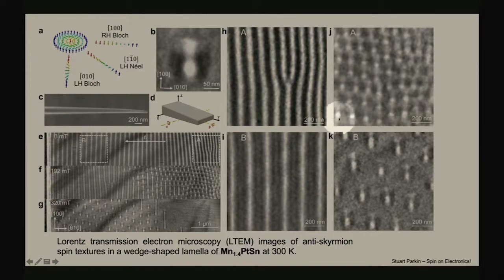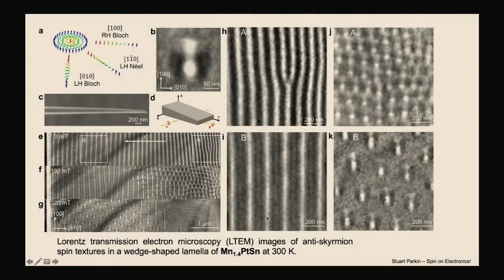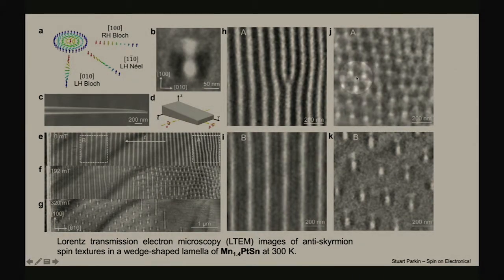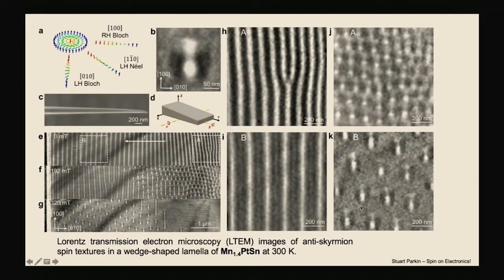We've oriented along the long axis of this wedge. You can clearly see that the separation of these helical, where the magnetization goes up to down, the period, is much smaller than here at the thicker end, where it's much wider. And similarly, if we use an appropriate magnetic field to stabilize the anti-skyrmion structure, you can see the anti-skyrmion's size is increasing from a small size for thin layers to a much wider size for thicker layers.